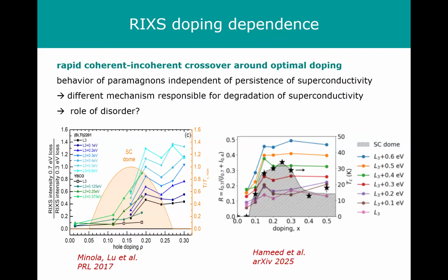I see. So you do have a complete crystallography of how the oxygen is arranged? No, we don't. With these thin films it's very difficult to do structural refinement, especially since they're grown on top of a substrate that has a very similar structure, so you can't do a refinement. So what we do is we do Raman scattering experiments. We see these defect modes, and from those data we can extract some information about the nature of these defects. Okay, thank you. Very nice.